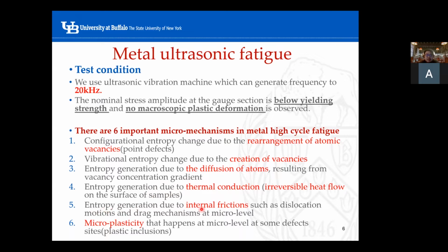The next one is entropy generation due to internal frictions. Yesterday I ignored these mechanisms because they don't have significant effect in the low frequency range. However, when we talk about ultrasonic vibration fatigue, some mechanisms like the drag of phonons, drag of electrons, drag of radiation come into play in this high cycle condition. Also, dislocation displacement and relative motion will cause entropy production, so this has to be considered in this test scenario.